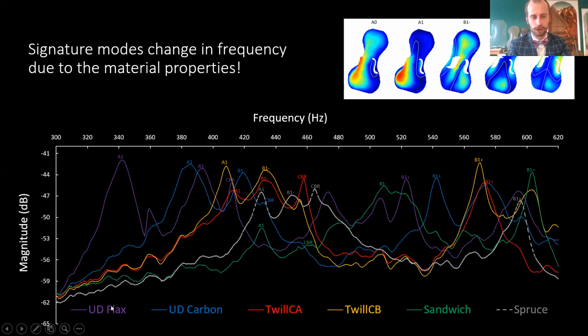And you see that for example, UD flax, which has the lowest stiffness in the longitudinal and transverse direction, so it is very flexible, and it is the highest weight, so this was 100 grams. It has lower frequencies for the signature modes than the other violins, followed by unidirectional carbon.